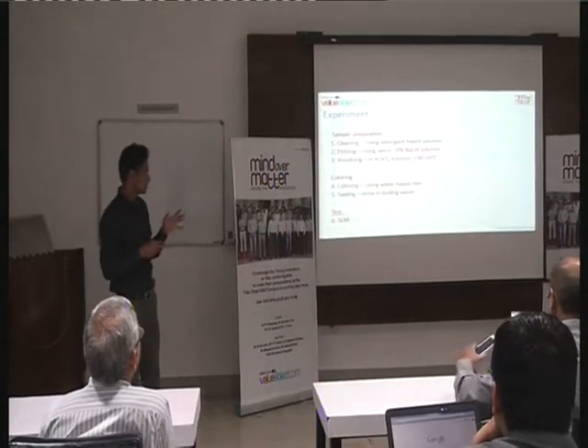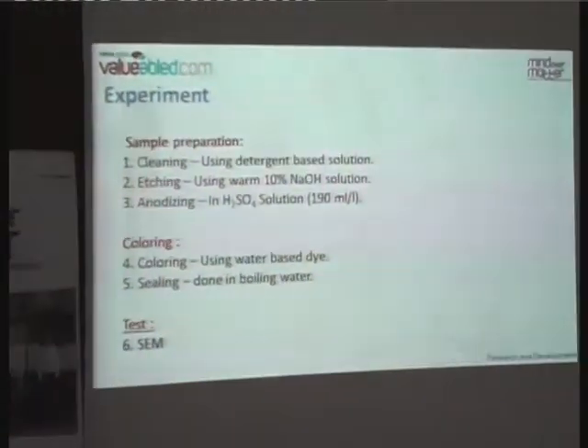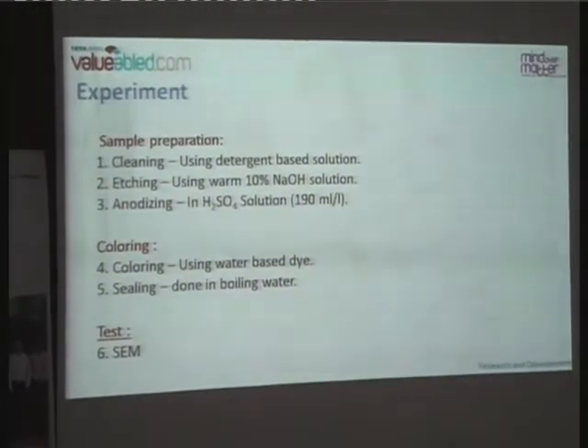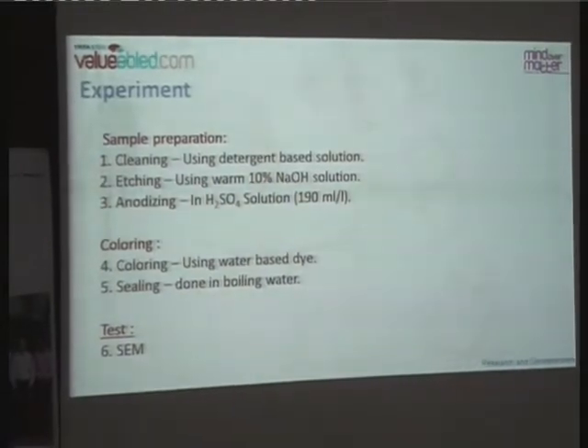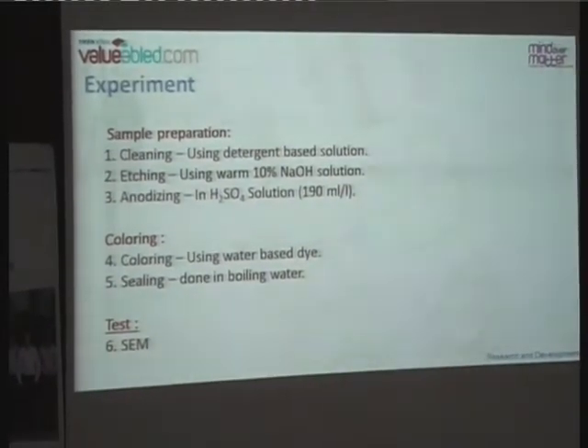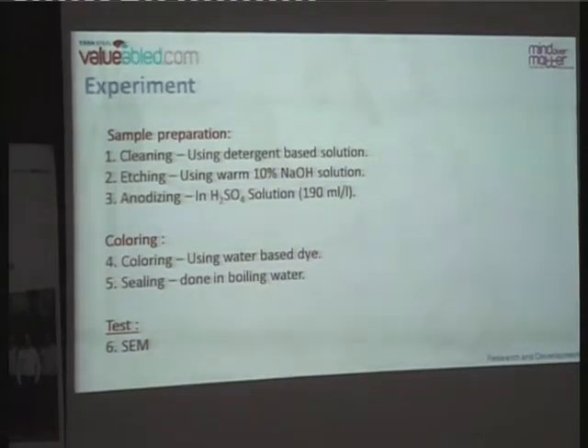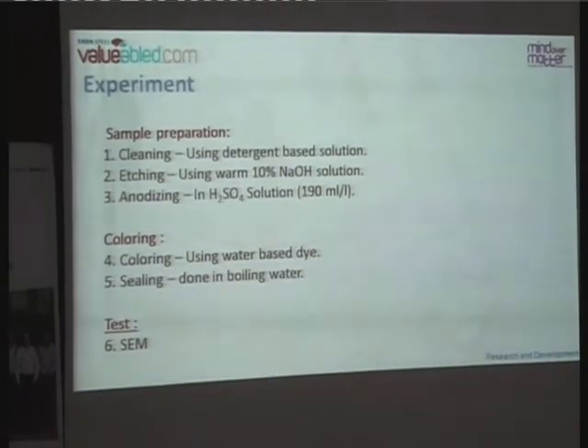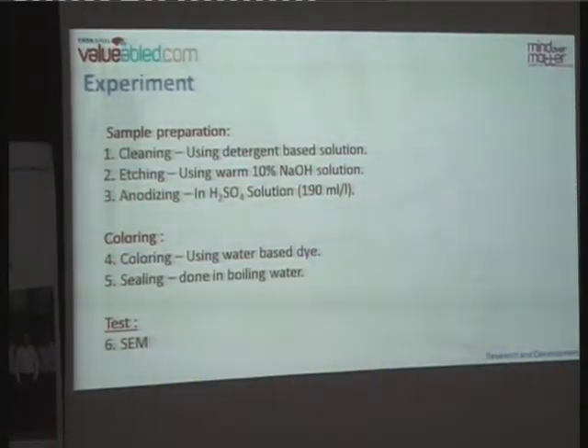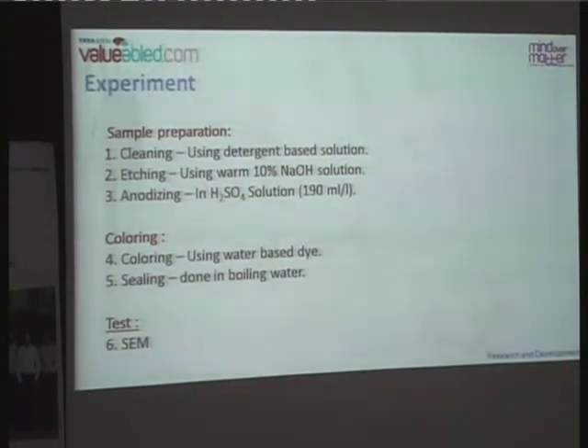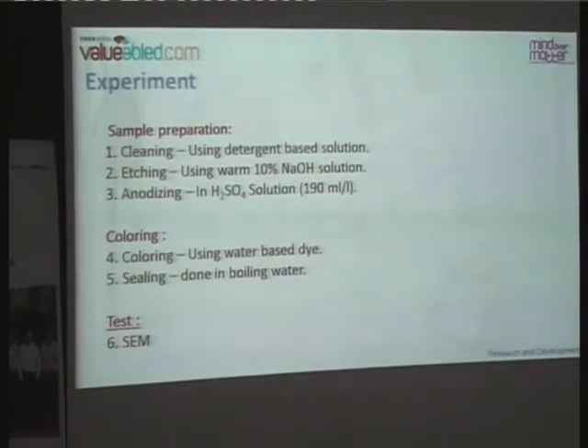For the experiment, for the sample preparation, the first step was cleaning. For this I used a detergent-based solution. Then for the etching, I used a 10% NaOH solution, and after that the anodizing process. For anodizing, we can use different organic or inorganic acids, but I have personally used an H2SO4 solution whose concentration was 190 ml per liter.